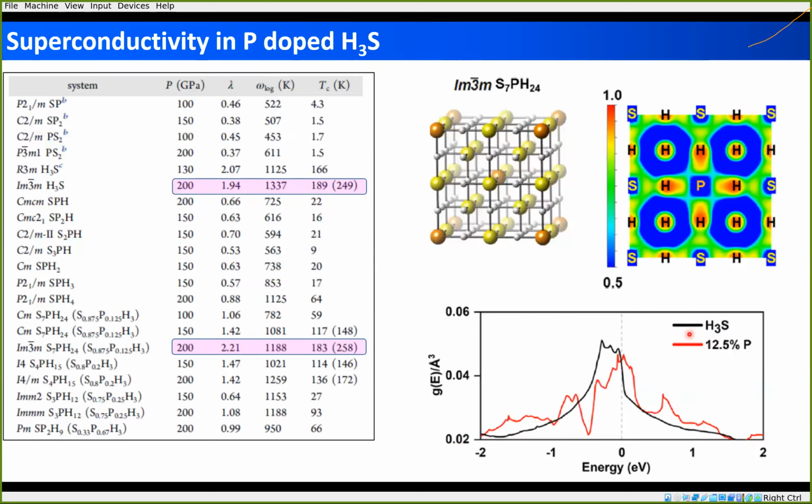And when we go into taking a look at those that we can calculate TC for, we restrict ourselves to metals, ones that have a high density of states at the Fermi level, higher symmetry systems. And one can compare, for example, the TC for just a phosphorus sulfide type of system at various pressures, and what would happen if you add a little bit of hydrogen to it.